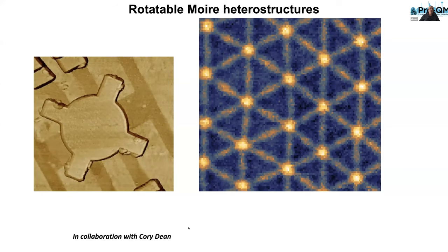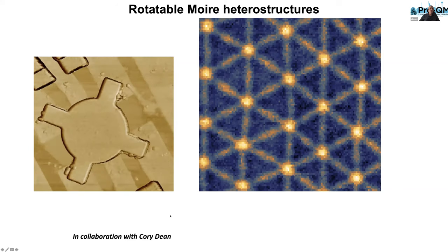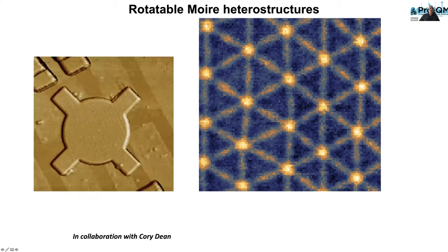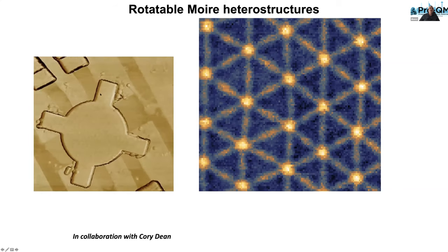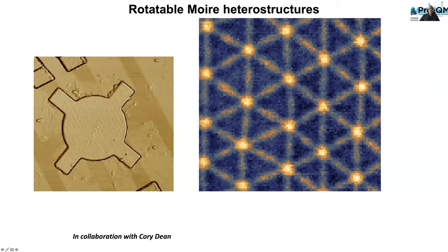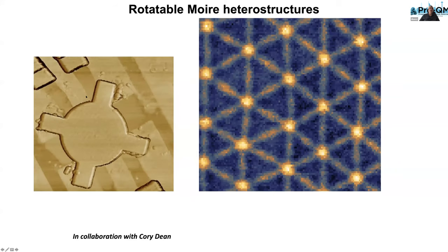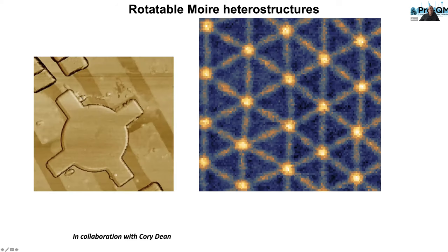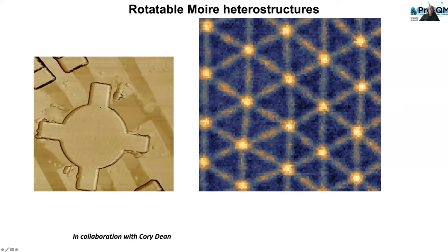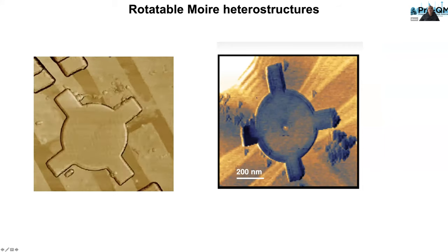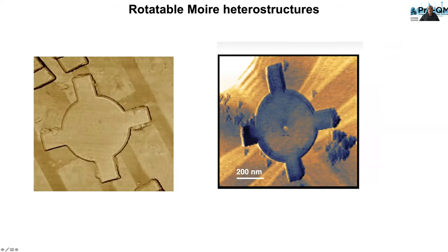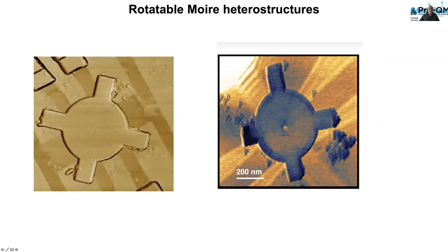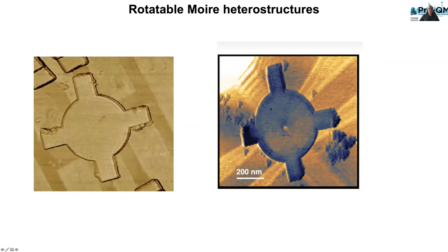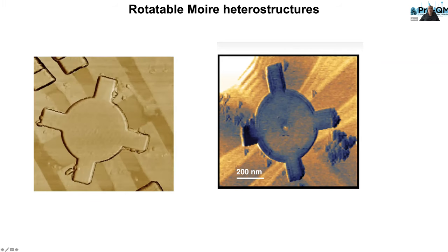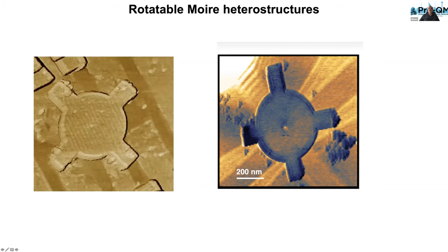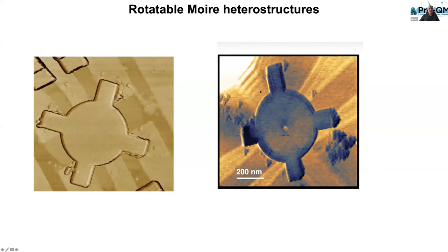And we took this notion of reconfigurable literally. With the help of my collaborators, Cory Dean and Jim Hone, they have been able to fabricate structures where you can rotate one layer with respect to another just by literally pushing on this layer with the tip of an atomic force microscope. So you see here in the left panel an AFM movie of a disk of van der Waals material being rotated above some complicated structures, and we can study plasmon polaritons and control of plasmon polaritons in this type of structures. We can change the reflection of these waves depending on the orientation of the disk. So this is an example of what we call a programmable quantum material. We literally dial the angle of this disk and the relative alignment of the layers, and we obtain different polaritonic behavior.